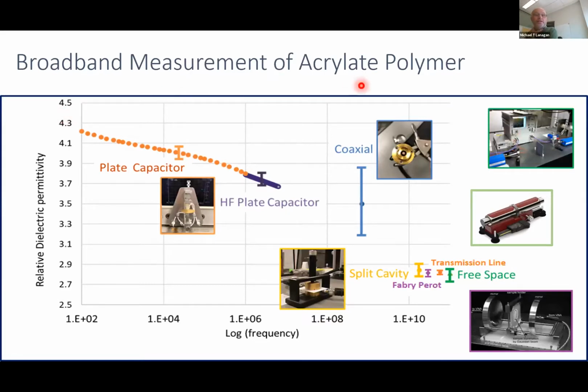So just to give you an idea, this was an acrylate polymer that was 3D printed. And we have all these different techniques. We're measuring the dielectric permittivity from very low frequencies, shown here 100 hertz, all the way up into the 100 gigahertz range. And what we can see here, the permittivity value at low frequency drops from about 4 for this acrylate polymer down to something around 3. And as you can see here, some techniques work better than others, but we have a lot of agreement in these techniques here